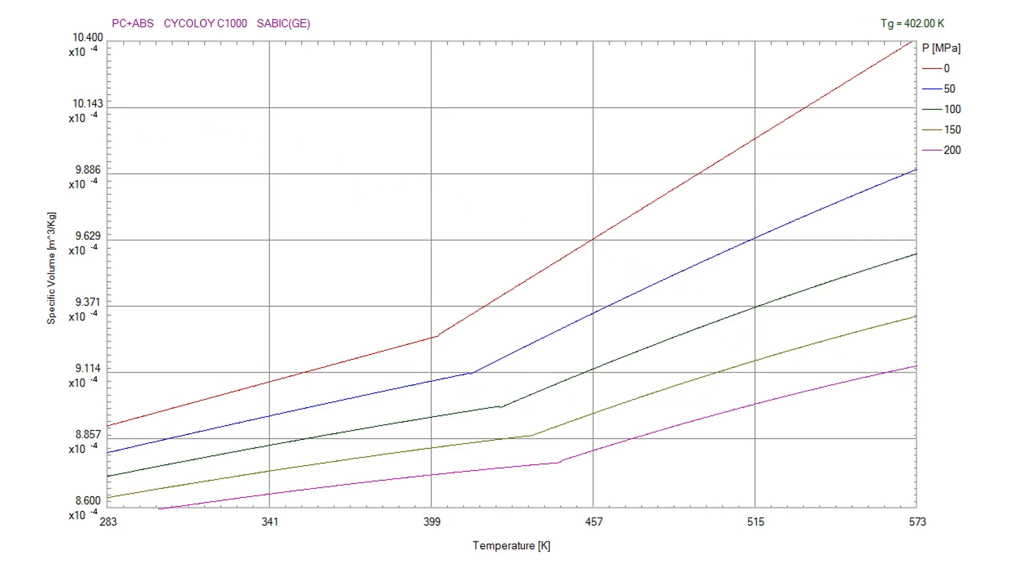The amorphous nature of materials is also well described in the PVT curve. These are typical PVT curves you can see on screen. The lines represent the individual pressures. The red line is zero pressure and blue line is 500 bar or 50 megapascals and then in 50 megapascal increments. If the pressure goes up in the molding cycle during the filling or packing process the specific volume will decrease that means the density will go up. This is typical behavior that shows amorphous materials have a very gradual packing and cooling behavior.